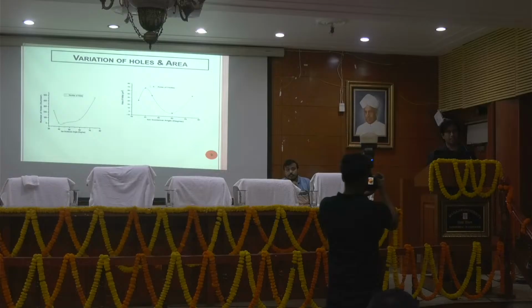These are the results coming from the investigation, the variation of holes and area. The left figure represents the holes created by the ion beam source taken at different angles. We see that the angles range from 35 degrees to 75 degrees, and the curve slowly bends at the normalized value between 40 degrees to 60 degrees, 50 degrees, 45 degrees. And the right side curve represents the area of the holes.